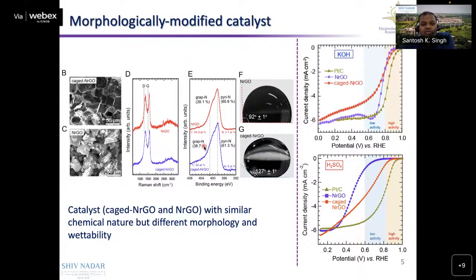After the development of these catalysts based on our previous model, we utilized them for oxygen reduction catalysis in the alkaline medium and the acidic medium. Here we can see that in the alkaline medium, as I told, these nitrogen carbon catalysts are very highly active. It shows very close activity to platinum, for both nitrogen graphene and the cage, the hydrophilic and the hydrophobic case.